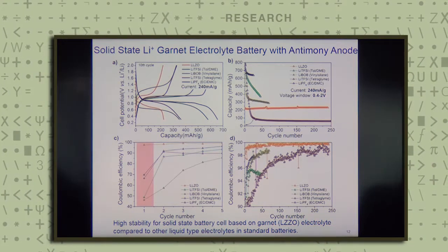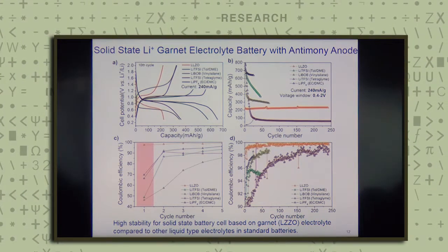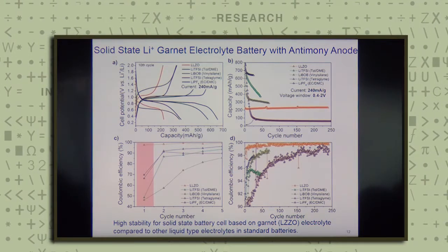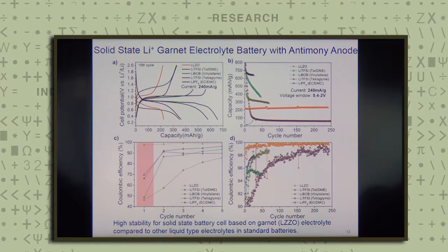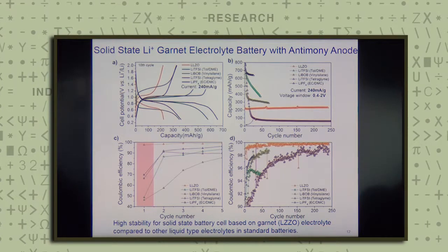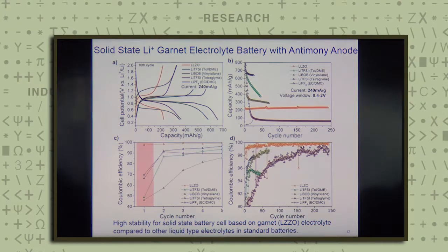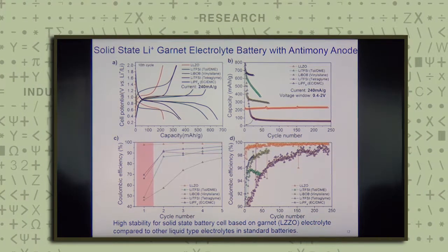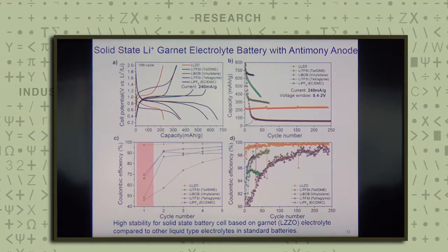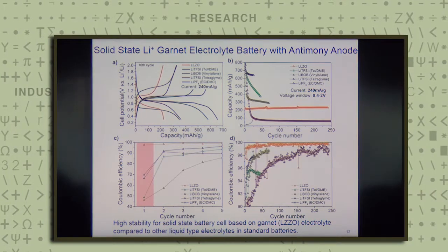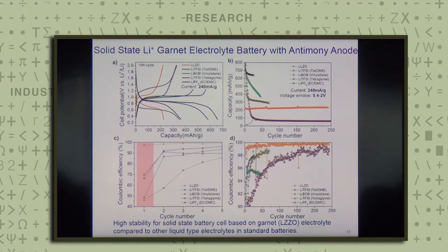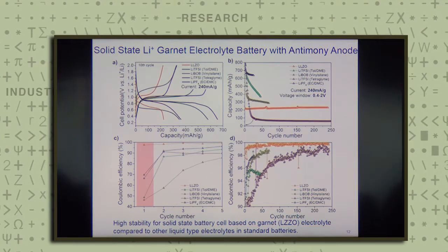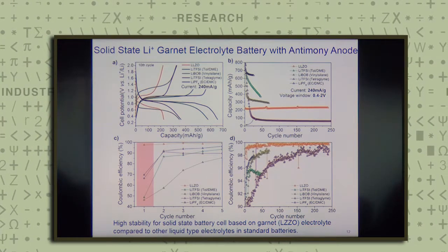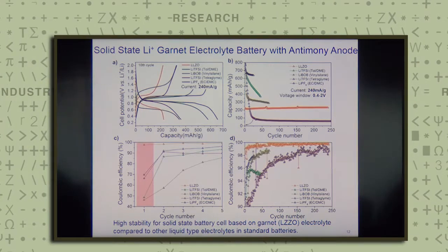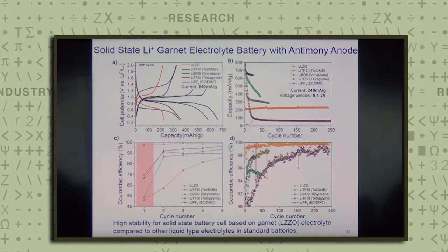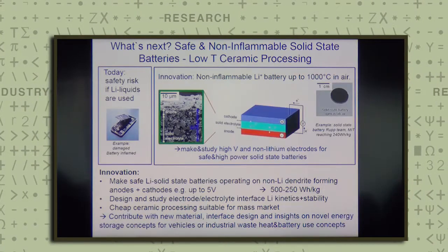So it's very high in the cycle number. It gives you stable cycling stability. And I think within the lithium garnets for a full ceramic composed solid-state battery cell, this is among the highest values so far published in this arena. So we're just about to publish those data. This gives you some perspective for large-scale storage that you can make safe batteries, reduced costs at lower temperatures in ceramic processing, and also that you can get very stable performances, which is interesting in the long run when compared to other liquid-based systems.